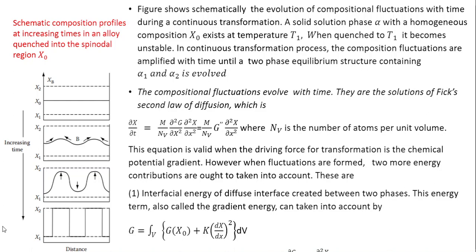Ultimately, when time increases, these solute depleted regions will attain a composition which is X1, and solute enriched regions will attain a composition X2. So consequently you have a structure which is an interpenetrated network of two solids having composition X1 and X2.